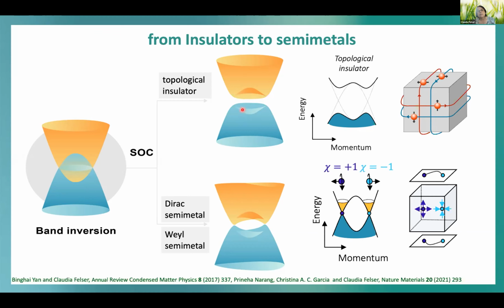And because if we have special conditions for the symmetry of the band, we get the surface states which connect the valence and the conduction band, and they are topologically protected. And in a topological insulator, they are all over the place - so the whole crystal has this topological surface state.